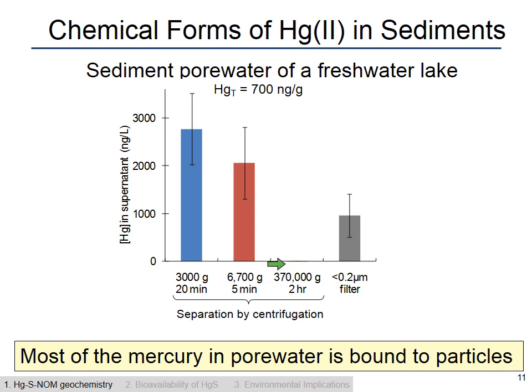And so the truly dissolved fraction in this case is actually something that's substantially smaller than what we would have quantified by a 0.2 micron filter. So the take home here is that when you're talking about sediment pore water, most of that mercury is actually bound to particles, colloidal particles and bigger particles.